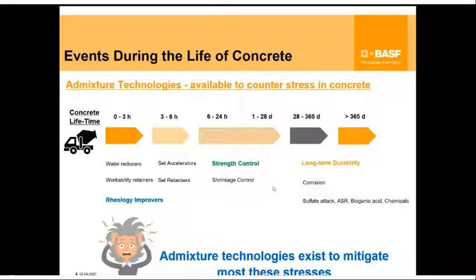After 28 days, there are not a lot of villains for concrete. You talk about long-term durability, but most of it would be related to external environments. So either external movements, corrosion because of aggressive environments with de-icing salts or seawater ingress, sulfate attack coming from external sources. Alkali silica reactivity is the only one that could be more internal in nature, but still requires a source of water to be able to move these ions around within the concrete. Biogenic acid corrosion, typically found in sewers and other systems where sulfuric acid is generated by bacteria.